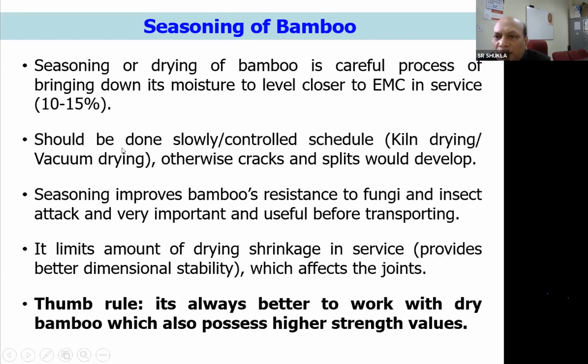So this process is called seasoning, and it should be done slowly and in a controlled way, like in kiln drying or vacuum drying. Otherwise, cracks and splits will come into the picture, and they will degrade the quality of the bamboo. Seasoning improves the bamboo's resistance to fungal and insect attack, and it is very useful for transporting, because we will not be transporting the water if we season the bamboo before transporting and before making any products. It also limits the amount of drying shrinkage in service, which affects the joints.